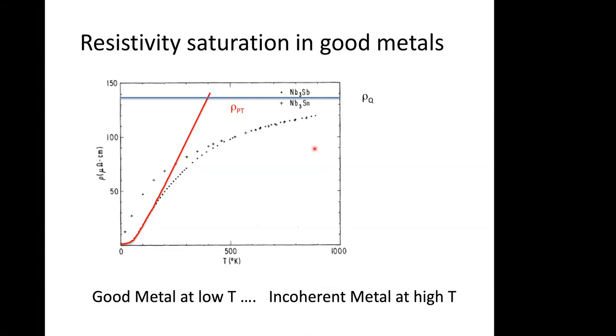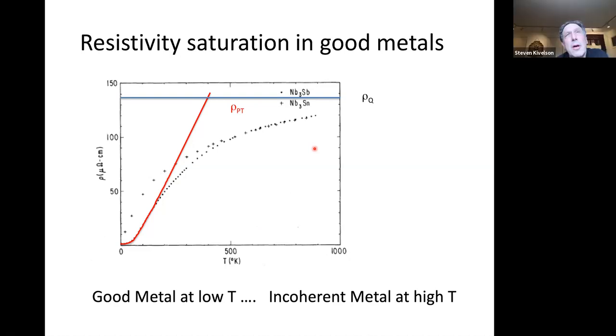Correct. So I have a huge problem with that, and let me explain what the problem is. Again, the problem is from microscopic theories, which you are not using very cleverly. I think of transport as connected with momentum relaxation, and I think of coherence as connected with energy relaxation, and they're totally different things. So when I say something is incoherent, I mean the imaginary part of the self energy is large. Shankar, within Fermi liquid theory, the transport lifetime is always longer than the quasi-particle lifetime. Yes. So if I infer a short transport lifetime, I'm sure of a short quasi-particle lifetime.